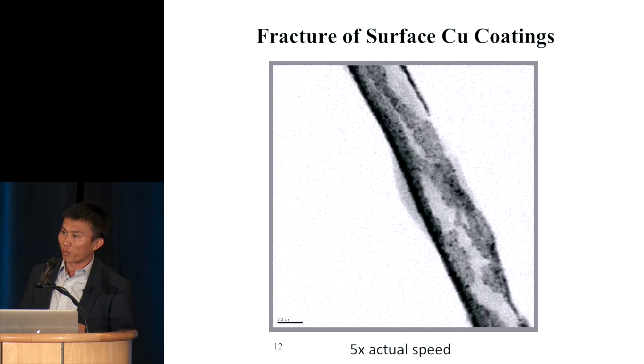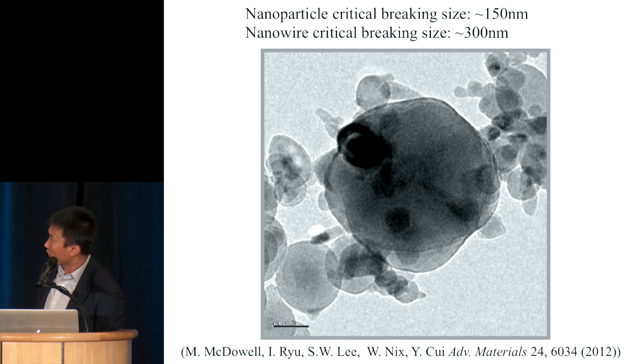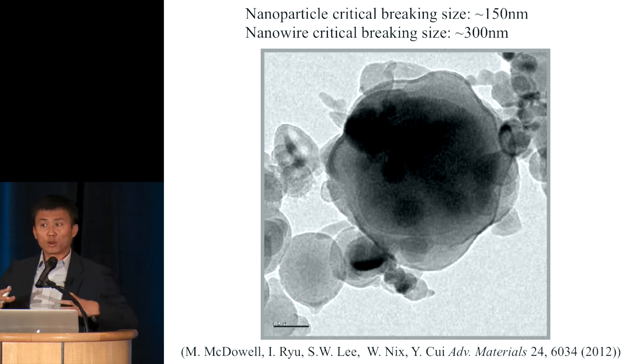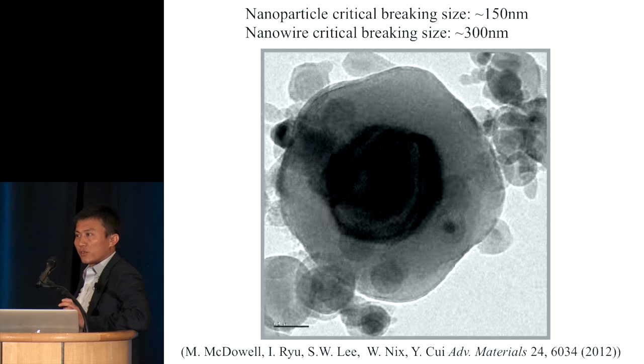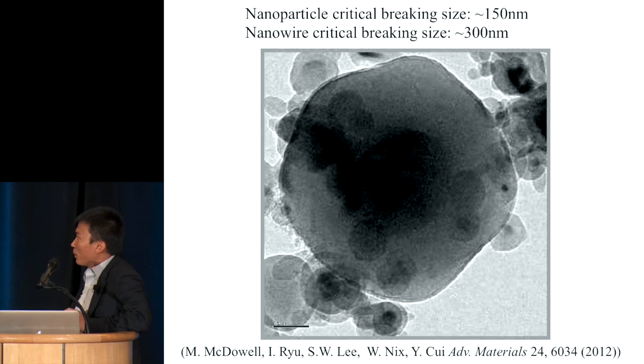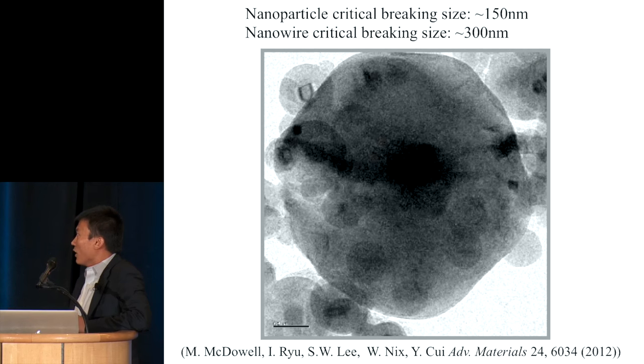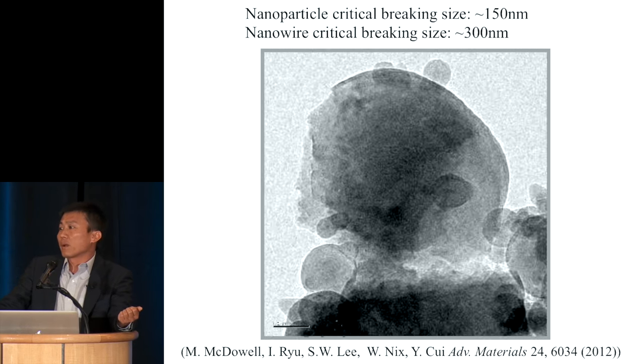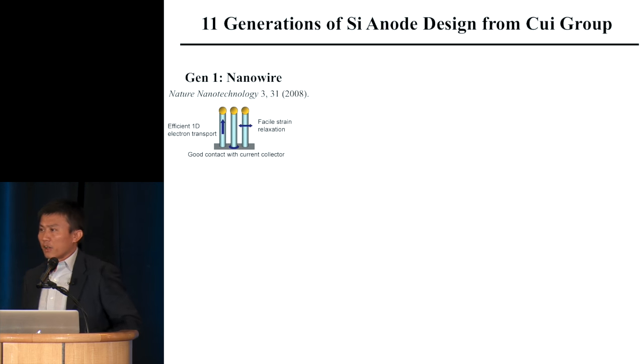I want to show you a video of silicon nanowires. During charging, the volume expands a lot — this is a 200 nanometer scale bar. It starts from 200 and expands a lot, but it doesn't break. The surface has a copper coating, and the copper is broken. This gives you the idea of how silicon can break batteries. In another video with silicon particles, including one 800 nm in diameter, once lithium comes in, the volume expands and the large particle cannot hold the stress and breaks, but the small one is stable. Once broken, you lose the material and electrical contact — the battery dies.